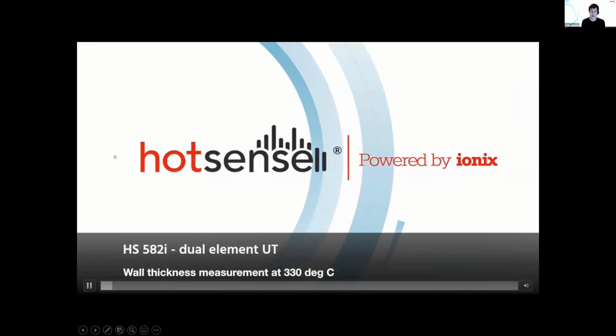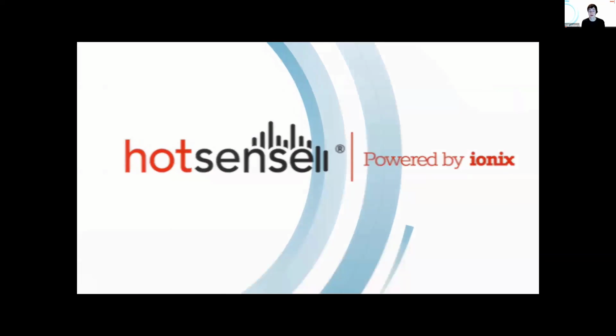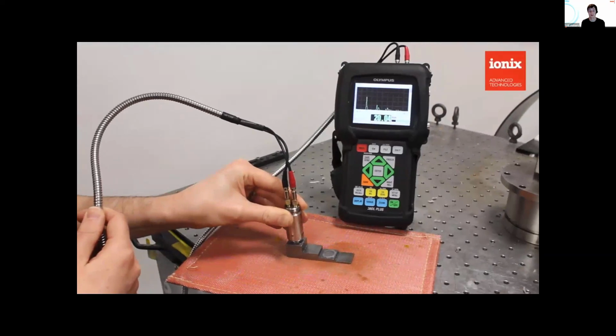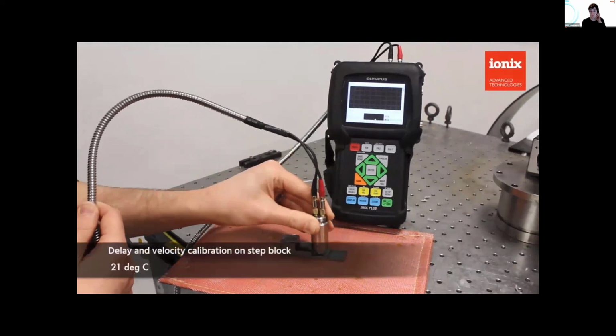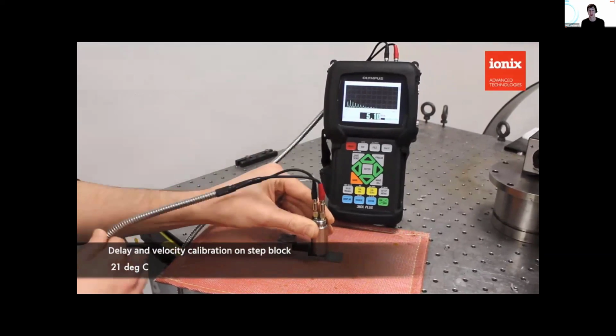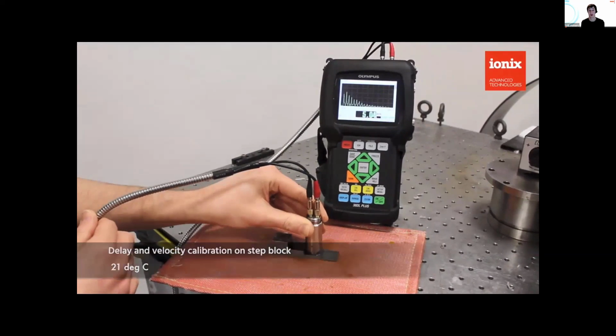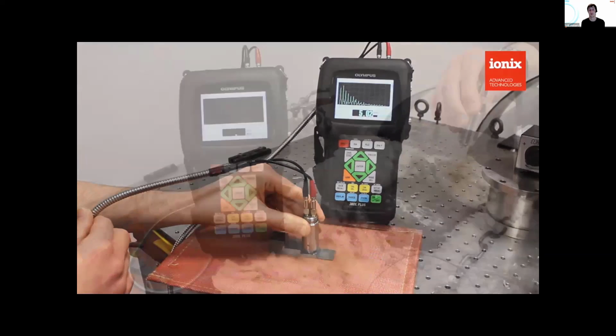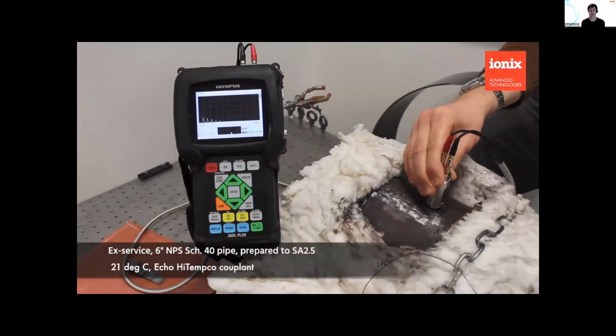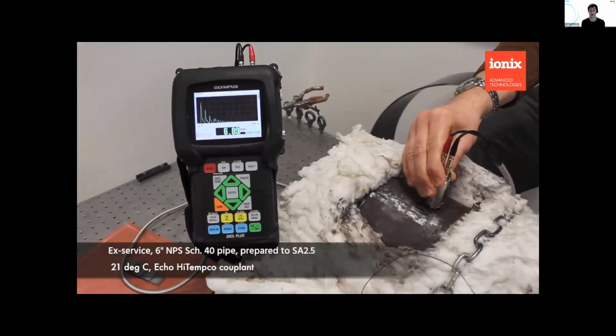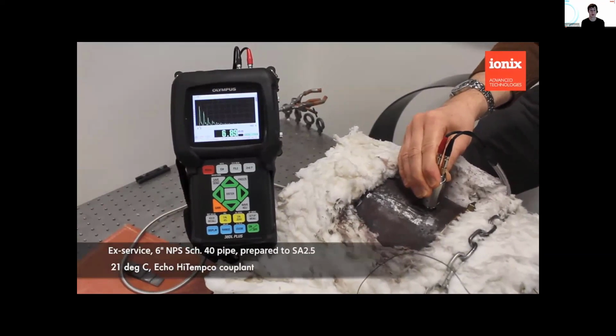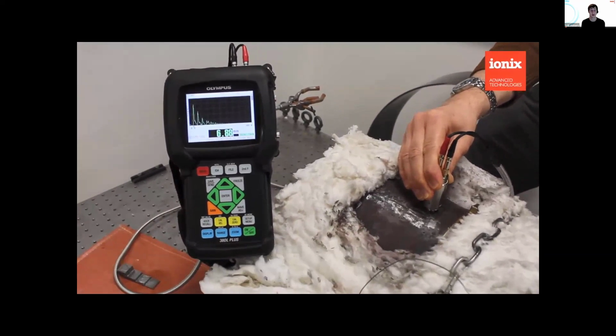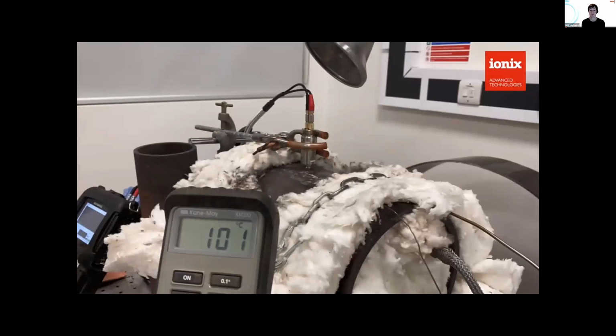Here is a video showing the probe in operation. As I said, it works like any standard UT probe. Here it is working with the Olympus 38DL Plus, which is a very common thickness gauge. It even works with the automatic recognition. So very simple. This is just at low temperature at the moment, 21 degrees C ambient temperature. Calibration on a step wedge, and then it works on a hot pipe.